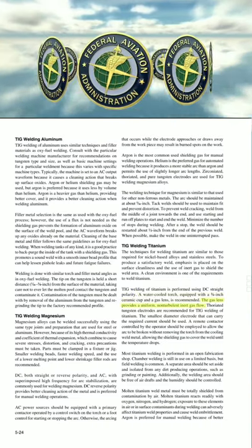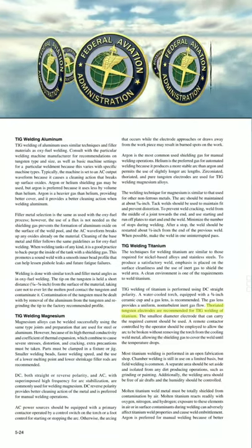A water-cooled torch, equipped with a 3/8-inch ceramic cup and a gas lens, is recommended. The gas lens provides a uniform, non-turbulent inert gas flow. Thoriated tungsten electrodes are recommended for TIG welding of titanium. The smallest diameter electrode that can carry the required current should be used.